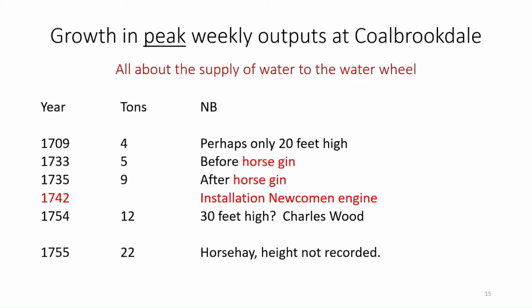And this was simply a horse-driven pump to pump water back from below the blast furnace up to the pool at the top of the hill. And at that point, the peak outputs went up from 5 tons to 9 tons. And then, as a natural follow-up, they installed a Newcomen engine to do the same job. And at that point, they got 12 tons at the peak. So clearly, they were increasing the size of the furnace, and therefore, almost certainly, being able to increase temperature at the bottom of the furnace.